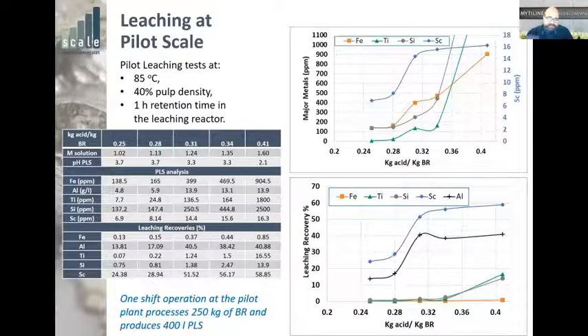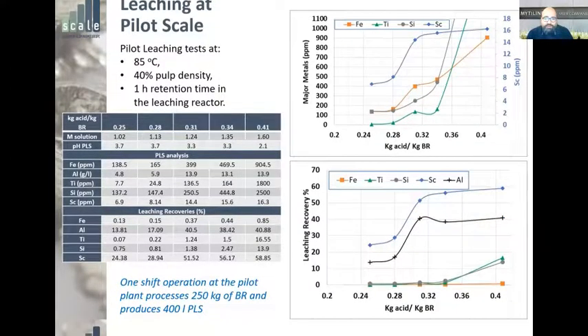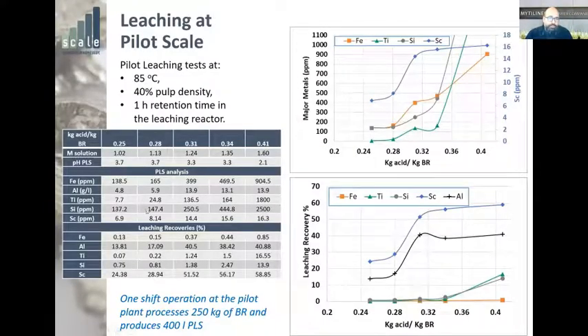And you can see again, these graphs are very similar to the ones presented in the beginning of this presentation. On the yellow side, you can see the spike, how scandium goes up, how iron is very low and then picks up after 0.3 kilograms acid per kilogram bauxite residue. So if you look at these results, you will see that at 0.28, we are getting very similar results as the two-cycle approach that was studied in the lab scale.